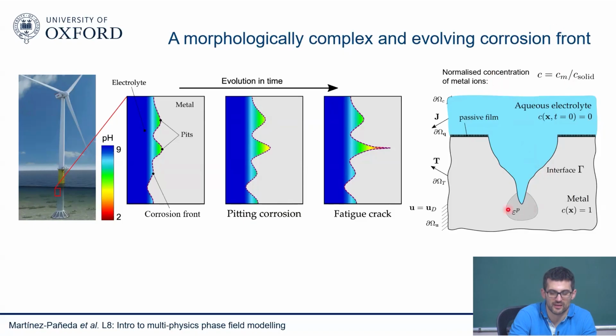But there will be a number at the interface, and they will travel along. And at the beginning, of course, you have 0 in the electrolyte. This is the quantity that you need to describe corrosion mathematically. The simplest model you could think of is a normalized concentration, which will be equal to 1 in the metal. As you generate metal ions due to corrosion, those metal atoms that you are detaching here will travel through the electrolyte and distribute within the electrolyte. That will be the simplest one.